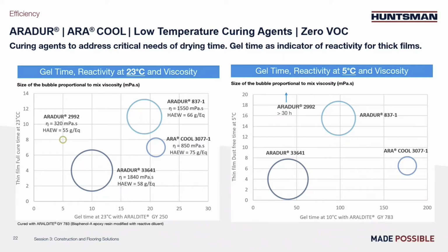On the right graph, it is a similar concept, but at lower temperature. So here the drying time is at 5 degrees and the pot life is at 10 degrees. So it's clear that Aradur 33641 is the most reactive, either at room temperature and at 5 degrees, but the mixed viscosity is high. So to me, it's a great product to be used as a co-hardener. Aradur 2992 is very low viscosity and great reactivity-wise, but the result at low temperature shows exudation when used in a thin film application. Aracool 3077-1 is a very good compromise.